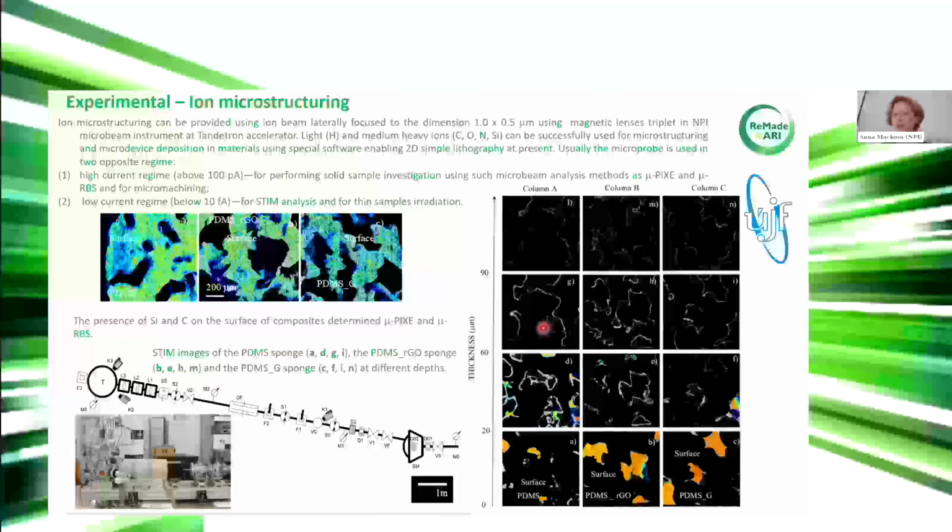Interesting is that these vertical domains, meaning domains in the direction in which the ions are coming, are squeezing very significantly in comparison with the basal domains, where there is also a decrease of the sizes, but not so significant.